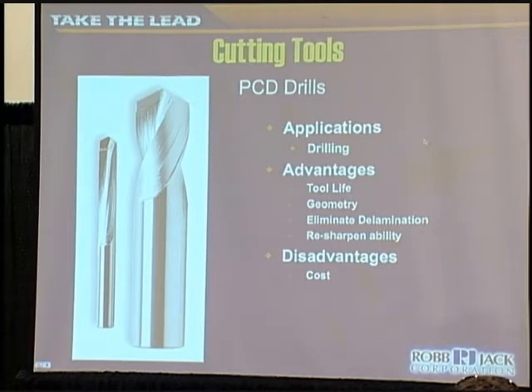On the PCD side, it's very similar to the diamond coating. We want to vary those angles, pierce through that material, and then ream that hole as we go through to get rid of all that delamination or broken fibers on the exit of the holes. The advantage to the PCD is you have resharpenability, so you can resharpen the drill after it's been used and you get multiple lives out of it. The downside is the initial cost is a little higher than the diamond coated.